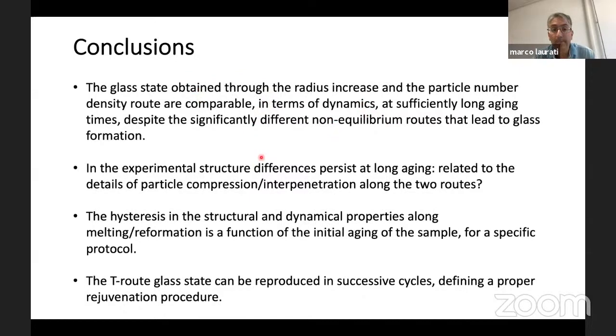So essentially, we could find that these glass states, in terms of dynamics, following the two routes, become comparable at sufficiently long aging times, but there is in the experiments this structural difference, which is instead persisting also at long aging time, and that must be related to somehow the intrinsic softness, I would say, of the experimental system, probably the internal structure. And especially the other significant result is that we can define this proper rejuvenation procedure.